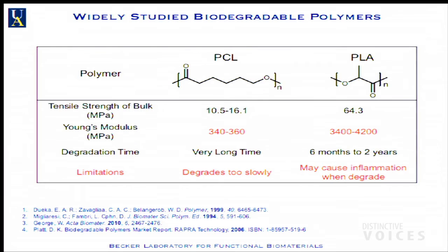Now, the reason they don't work is that they are semi-crystalline. So this is caprolactone, and I won't test anybody. This is lactic acid. So lactic acid is a natural body metabolite that builds up in your body when you exercise, and that's what makes you sore. They have well-defined tensile strengths, mechanical properties, degradation time. But for what we're trying to do here, the degradation time is too long. And because they strain, harden, and crystallize, you get parts that are amorphous, which degrade faster than the parts that are crystalline. And therefore, you have a real challenge in trying to balance those mechanical and degradation properties during the